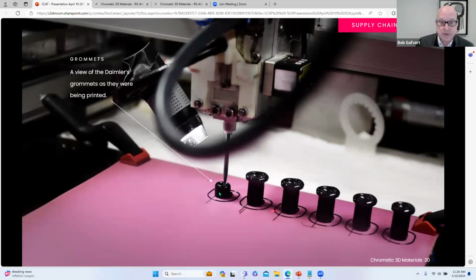We're working with a liquid material. We have a software suite that's controlling not only the speed of the extrusion and the speed of the XYZ of the printer, but also the chemical reaction of those materials as they're curing. These parts are realistically curable very quickly. They're curing as they're coming out of that mix tip. And to get final properties from a post-processing standpoint, the only thing that we recommend is going into a thermal oven at 100 C for 8 to 10 to 24 hours, depending on your geometry.